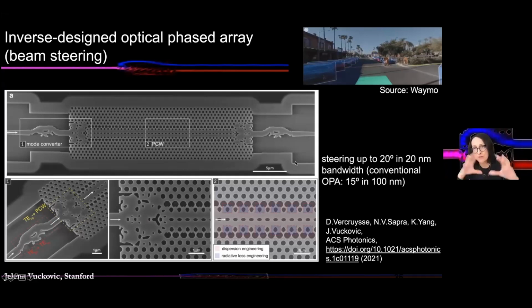So there are all these different elements that almost look like errors in fabrication, but they're actually an optimal pattern within fabrication constraints of our process. And this enables steering of the beam by 20 degrees when you tune the input wavelength by 20 nanometers, which requires a much less expensive laser than the previous state of the art, where you could steer the beam by 15 degrees if you tune the laser by 100 nanometers.